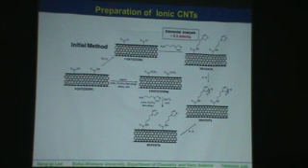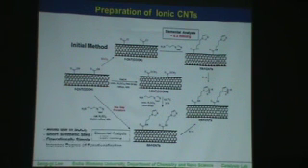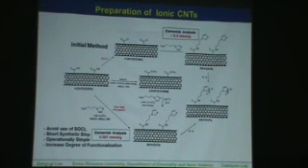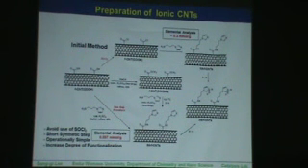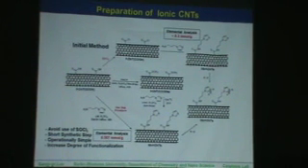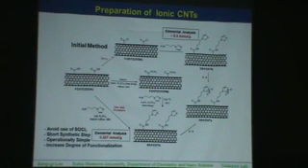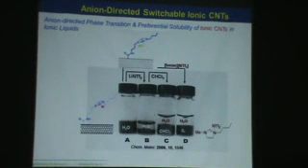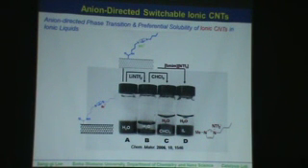And this can also be carried out in one step. The carboxylate-functionalized CNT was mixed with 3-aminopropyl imidazole in the presence of methanesulfonic acid in methanol solution, refluxed for 48 hours to give this imidazole-functionalized CNT, and then we do the metathesis to get this imidazolium salt-functionalized CNT. And once we get this one, the property of this ionic CNT can be easily tuned by simple anion exchange.